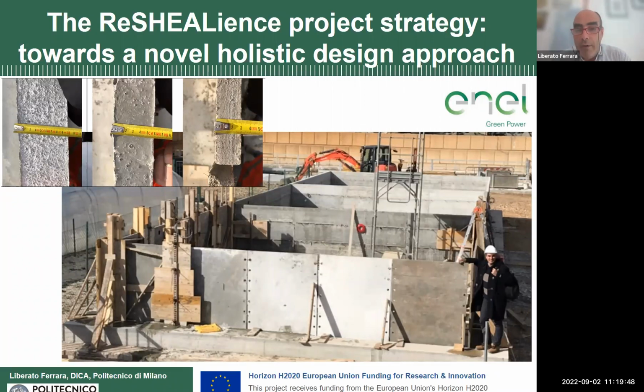Then we used one of our UHDC materials, and we built an absolutely identical tank compartment, but in this case, the thickness you can see from the middle picture here on the top was just 6 centimeters. So in the end, we are using 40% less material volume to build the same structure.